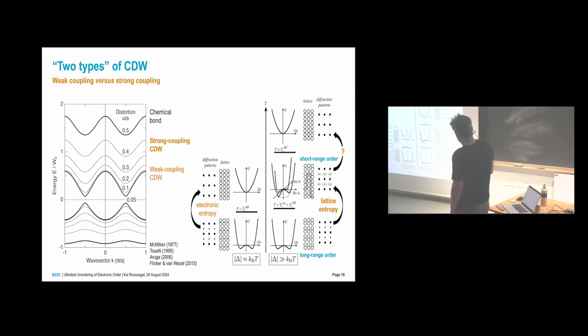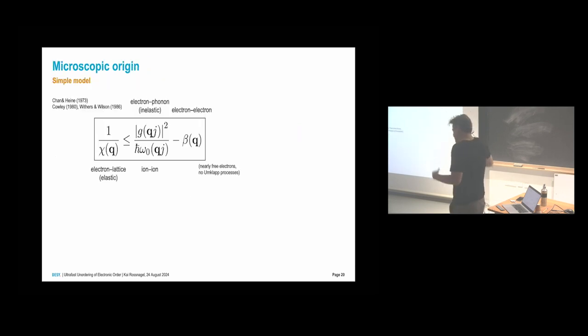First, you destroy the long-range phase coherence. You create domains, and this is indicated through this diffuse intensity, for example, in diffraction patterns. And then in a second step, you also remove this short-range order and undo your charge density and periodic lattice distortion. So it's a two-step process, and it's driven by entropy, lattice entropy, and this will come again in the time domain.